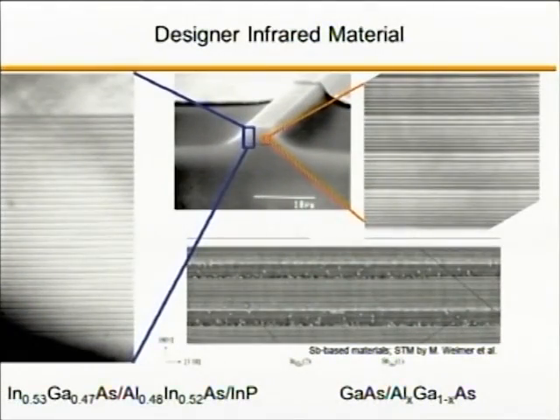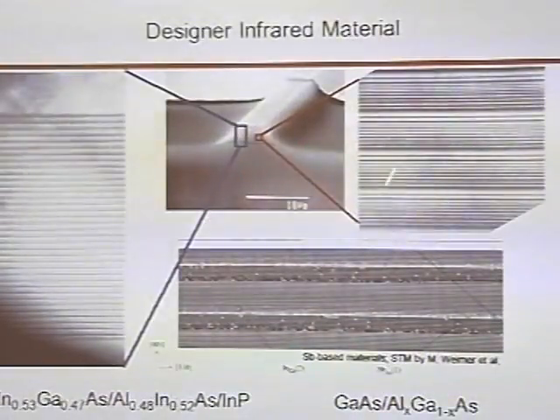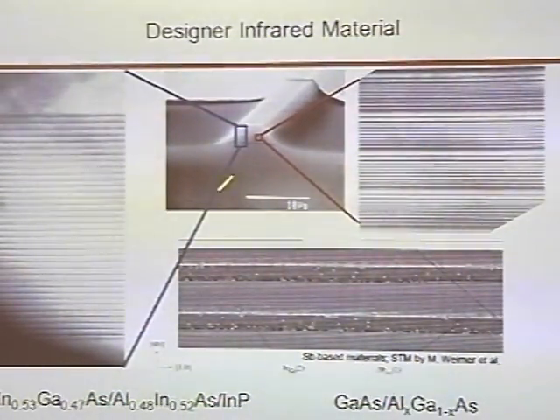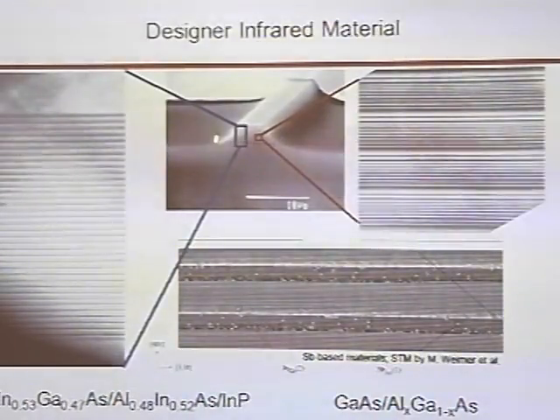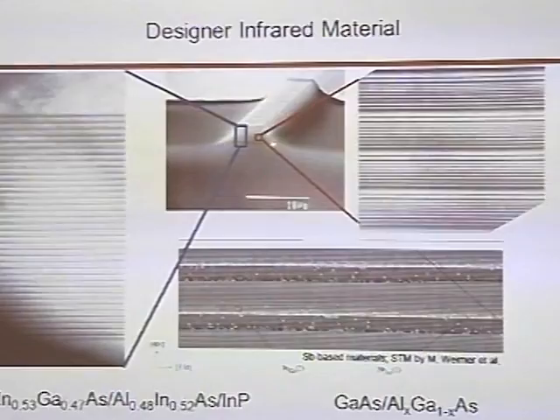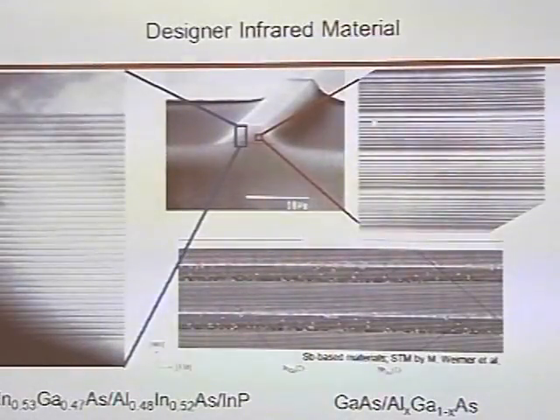This was the initial structure made by Al Cho by molecular beam epitaxy. This is how a QC laser works. So it is a ridge. Typically, it's a couple of millimeters long. The width depends on the application, but you're talking typically 10, maybe 15, 20 micron. And so you can see the thinnest layer then. This was designed to emit around 5 micron wavelengths. So if you want to emit at longer wavelengths, you would need these two layers thicker.